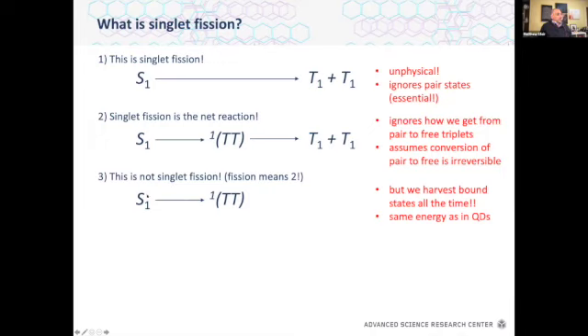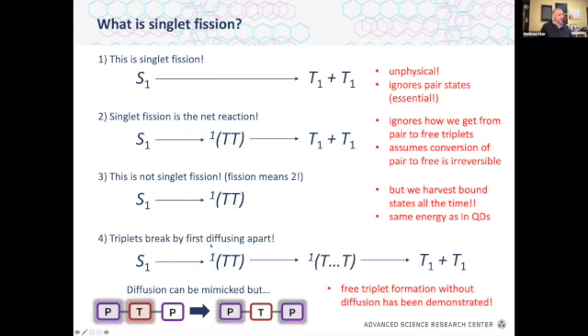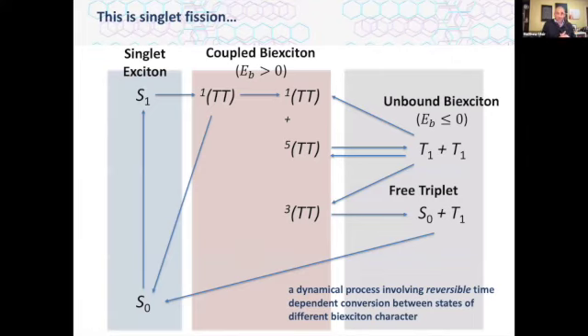People tend to say that the formation of the triplet pair is not singlet fission, that fission means two, and this is not two. But as I tried to set up in the beginning, we harvest bound states all the time. That's not a problematic thing, that we have a bound state. What's problematic is if the bound state is too strong to dissociate. You could say the triplets break by first diffusing apart. That's also not true. That helps, but it's not a strict requirement. So this idea of what singlet fission is kind of a wrong question to ask.